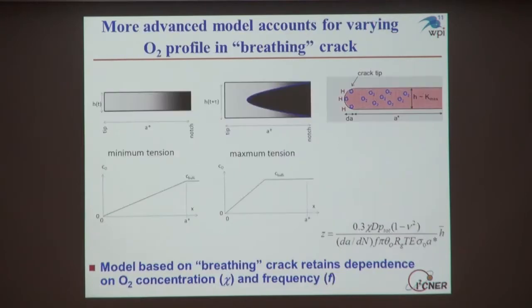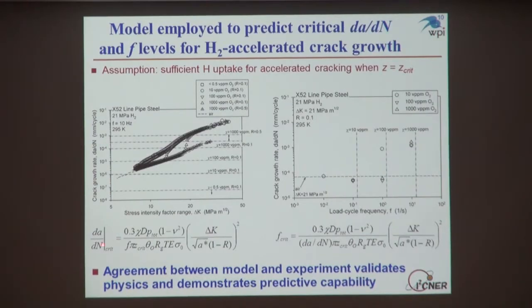And I'm comparing it against the experimental results, not only for the crack growth rate versus the stress range data, but also for the crack growth rate versus the load cycle frequency data. And for each of these cases, we can formulate the model so that if we assume that in order to get sufficient hydrogen uptake to enable the accelerated cracking, this happens for a critical adsorbed oxygen level on the crack tip. In other words, when that oxygen level is decreased low enough, we can get sufficient hydrogen uptake to activate the accelerated cracking. And this is how we can try to predict the mechanical crack growth rate that would lead to the accelerating cracking in these types of experiments.